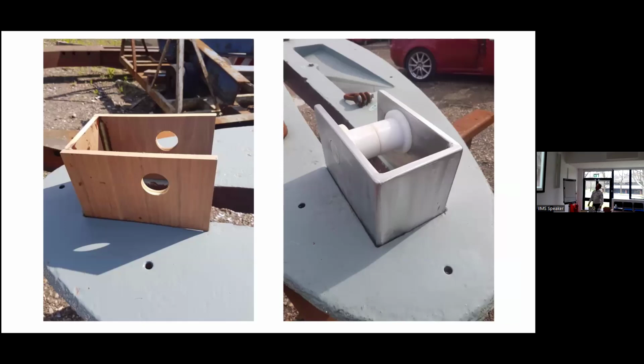And the next slide. And so the pivot, I made a pattern, had a stainless pivot box made that sits in a rebate on the casting. It actually is held captive within the boat because there's a moulded trunk in the bottom of the hull that actually holds the sides of this stainless steel assembly captive once the keel is bolted up. But I also use a fantastic product. It's difficult to see, but I bedded this on an adhesive that we do called G-Flex.